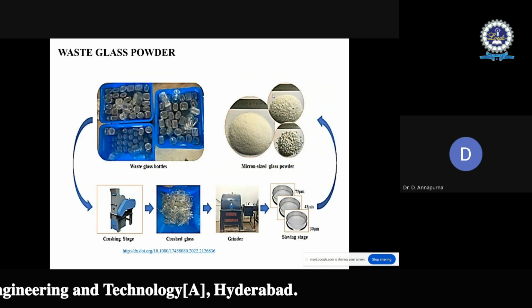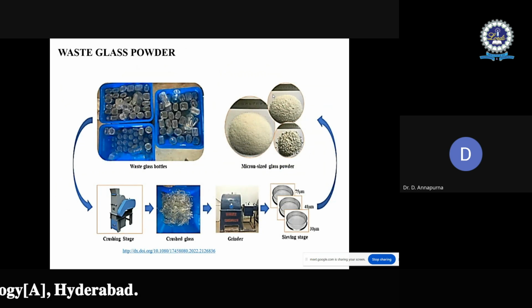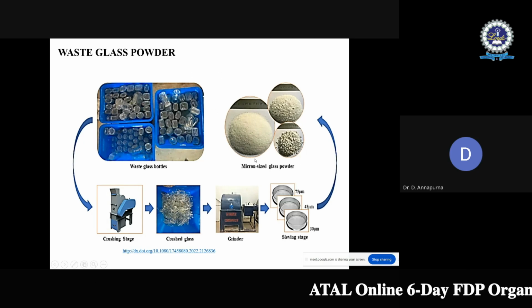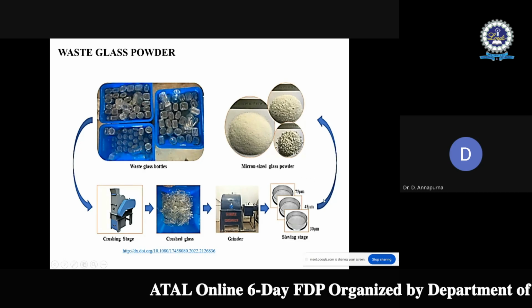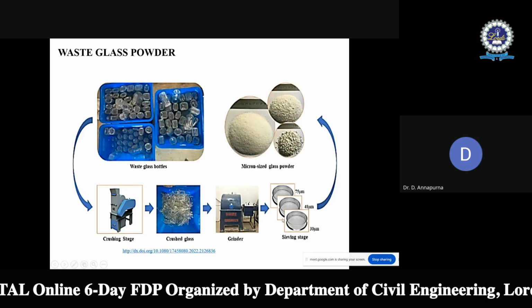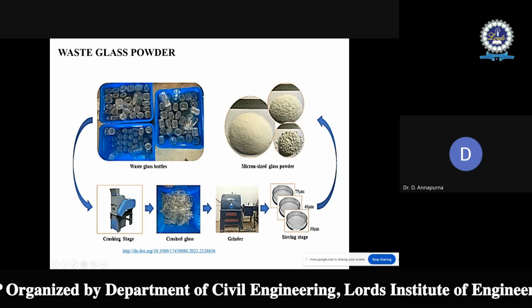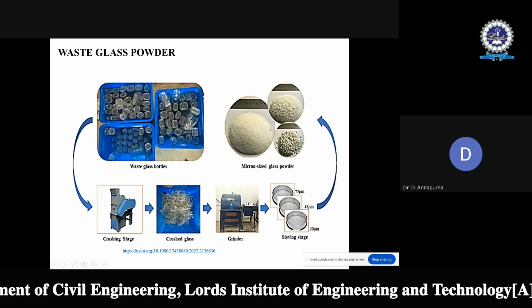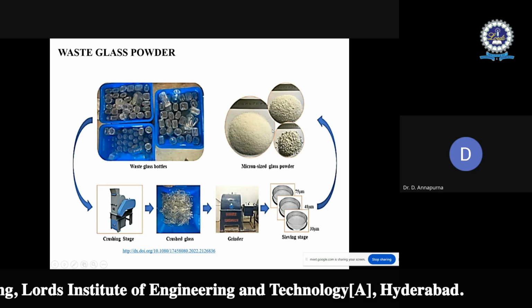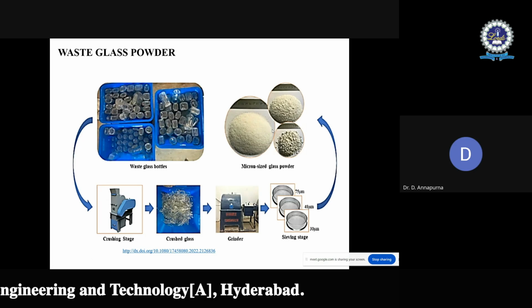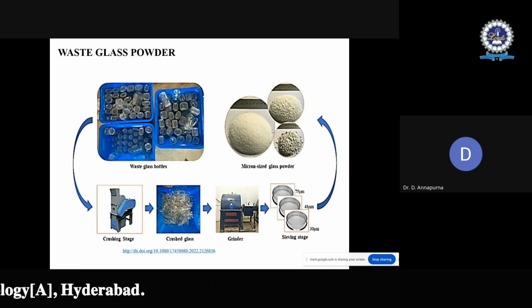The waste glass powder production process typically involves collecting the waste glass, sorting it to remove contaminants, crushing it into small pieces, then washing to further clean it, and finally grinding and sieving it to get the glass powdered form. It is rich in silica and alumina, so it can be added as a source material in the production of geopolymer concrete.